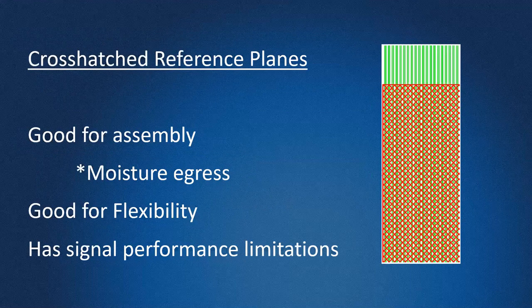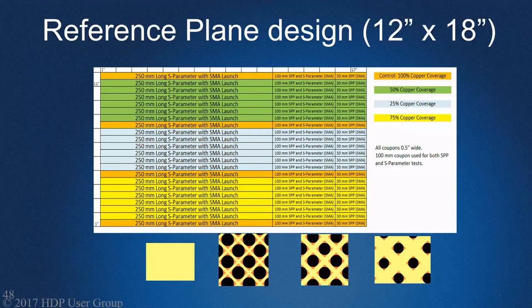There's a very good HD PUG study on this that DuPont participated in. It was presented publicly at IPC a few years back. You can find that presentation. If anyone has trouble finding that, I can help. It's also a moisture egress path, very beneficial for assembly. When you bake your flex circuits prior to assembly, which I always recommend people do, this allows for moisture egress. Part of the HD PUG study was that round openings were better for high frequency, and they were just as effective for flexing and moisture egress.